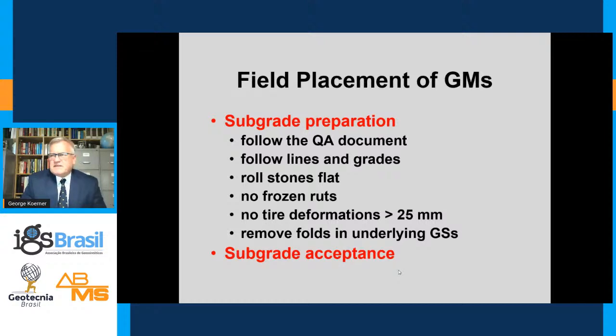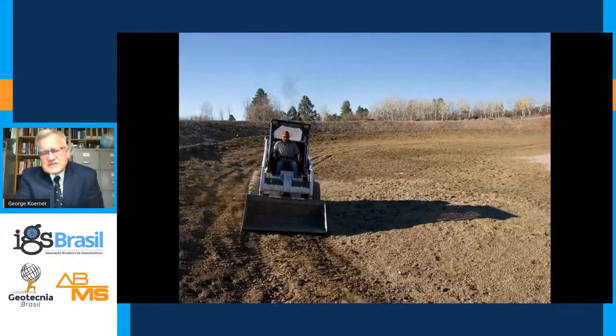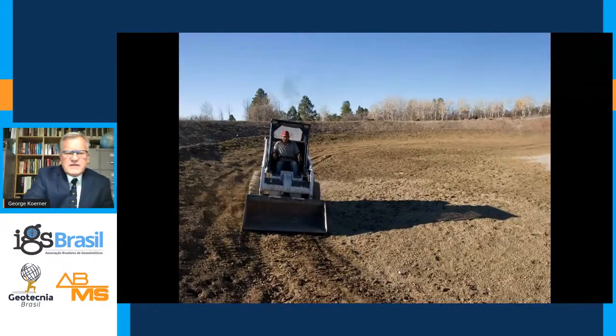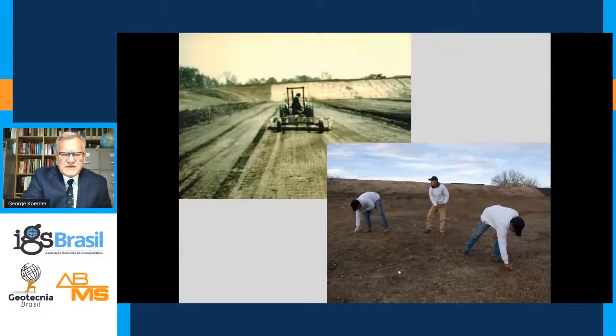This is something that the QA personnel needs to obtain from the earthwork contractor, and that has to be signed off by the owner. To do this, you start off with a site which could have some bony material, some greater than 25 millimeter size material. This material needs to be picked out. You can do that automatically with a stone picker or by hand.